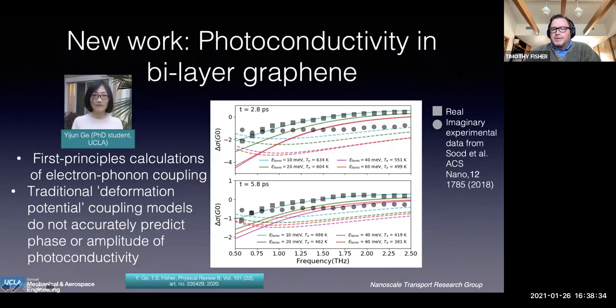Okay, so what else is new in this regard? Yi Jun is a student of mine who does DFT, and she's just about done. She worked on photoconductivity in bilayer graphene. It turns out that bilayer graphene, unlike single layer graphene or graphite, has a really interesting photoconductivity response. You shine light on it and it becomes much more conductive. I know this is an eye chart, but the photoconductivity is the change in conductivity as a function of the frequency of light that's hitting it. And her curves, the ones to focus on, required some fitting of apparent Fermi levels. But certainly the cyan colored curve here matches the experimental data, which are in the symbols, the real and imaginary parts of the photoconductivity, very, very well.